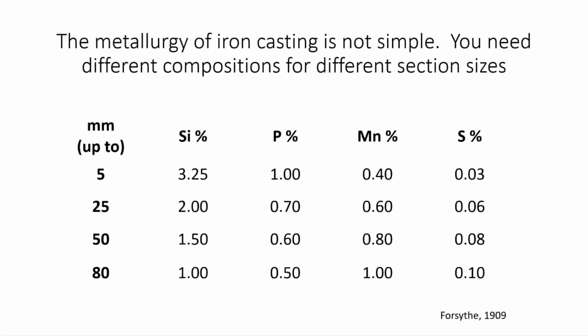Now, the metallurgy of cast iron is actually not at all simple. You need to have a different composition for every section size that you cast if you want to get the optimum strength. This table was published in 1909 by an American called Forsythe, and it basically shows that if you want to make a thin casting, you have to have a lot of phosphorus and silicon. But if you want to make a thicker casting, then you reduce the amount of phosphorus and silicon. I can't get excited about manganese and sulfur. It's all too complicated.